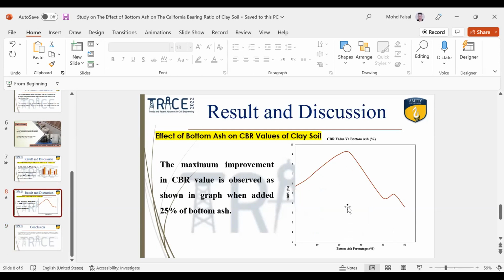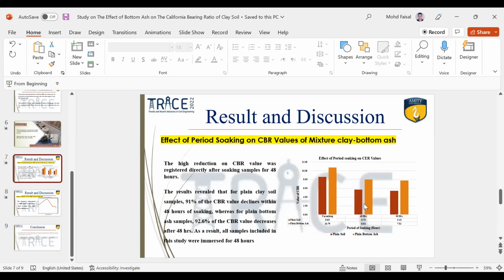At 25%, it was around 9.12. And for the plain soil, it was before the bottom ash, around 5.73, and this is for the clay soil without bottom ash. So any reason why after 25% it is decreasing?